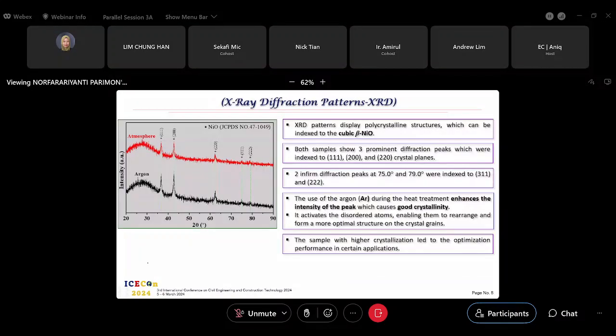For the structural analysis in terms of the XRD diffraction pattern, we can see that both samples display polycrystalline structures which can be indexed to cubic nickel oxide. Both samples have three prominent diffraction peaks at 111, 200, and 220, while two weaker diffraction peaks are at 311 and 222. We can observe that with the use of argon, the intensity of the peaks is higher, and it can enhance the crystallinity of the sample.